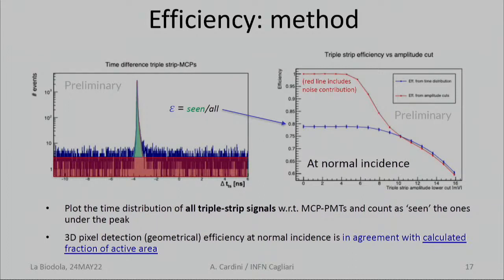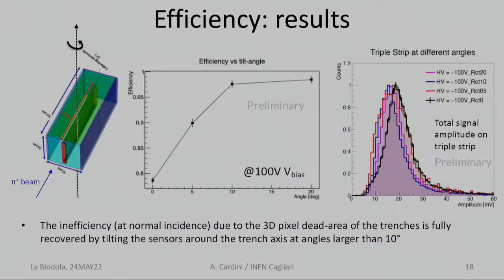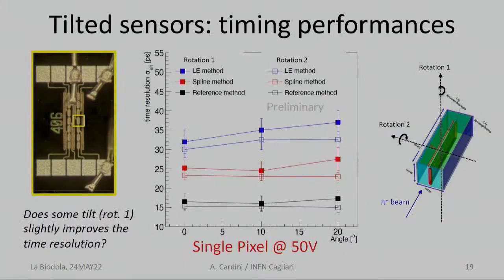What we see is that we reach, let's say, 80%, which is perfectly compatible with the active area of our pixel. So this is exactly in agreement. And when we tilt the detector with respect to the beam to achieve a non-normal incidence, you see that we go very high, and we are reaching practically an efficiency of 100% for these devices, as expected. So this tilted operation is the usual way to operate this 3D sensor.